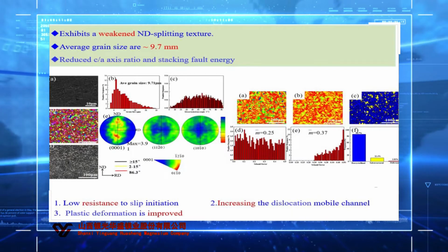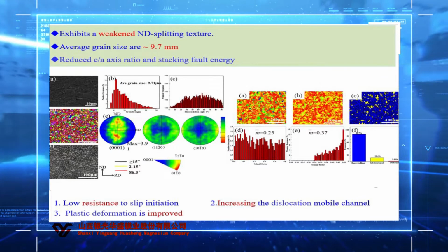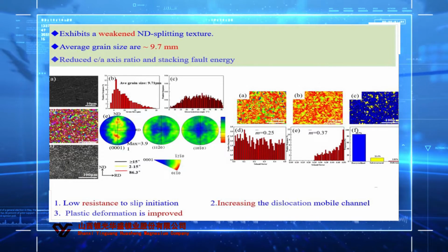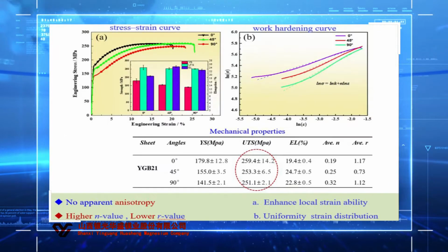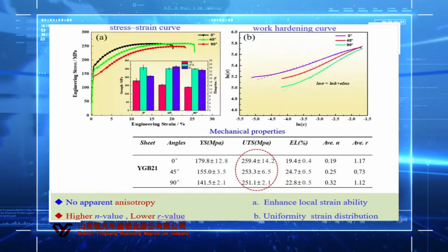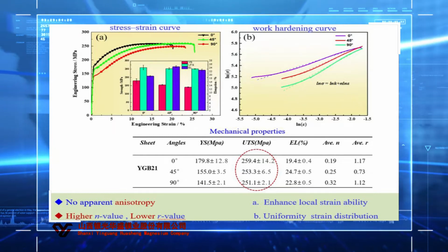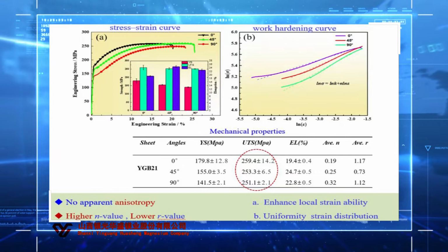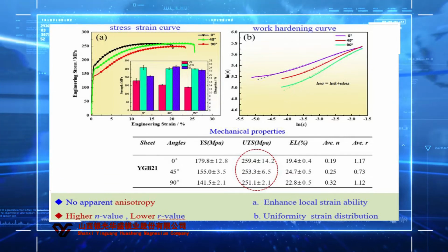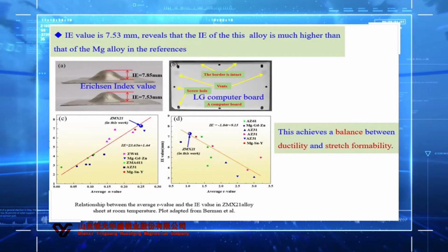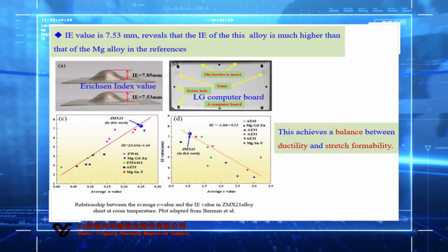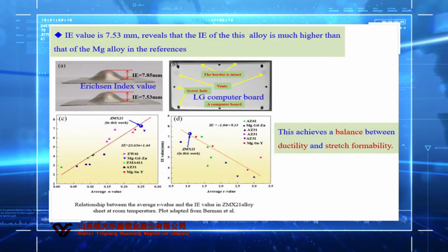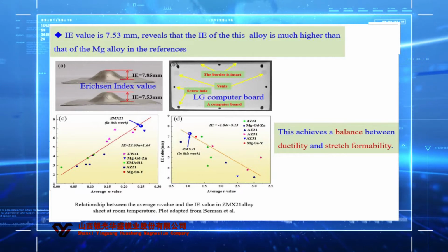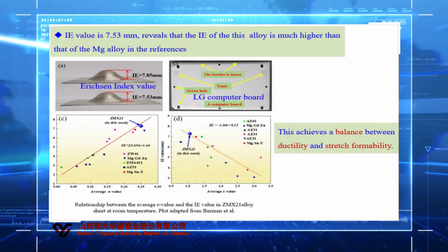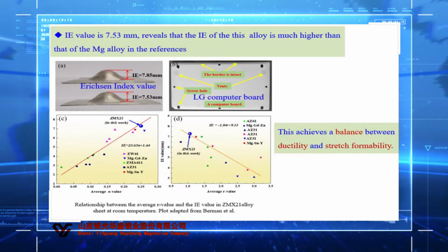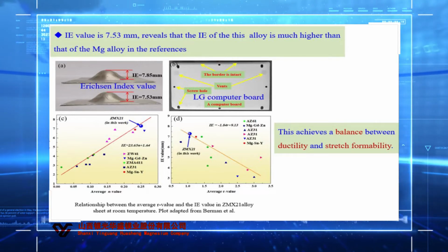From the microstructure, we can see that the initiation of non-basal slip is permitted, and the plastic deformation ability is improved. And from the mechanical properties, we can see this alloy has high UTS, higher n value, lower r value, enhanced local strain ability, and promotes uniform plastic deformation, and this is the stamping formability. We can know the Erichsen index value is 7.53 mm. This shows that the IE of this alloy is much higher than that of the traditional magnesium alloy, and this achieves a balance between ductility and stretch formability.